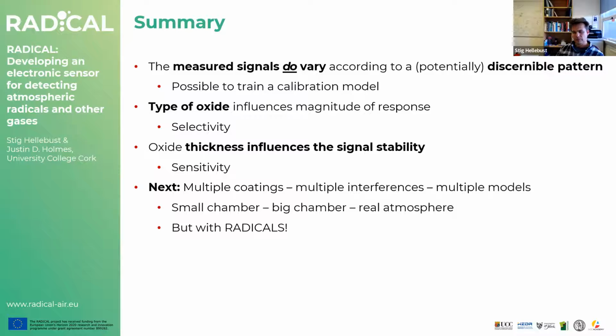So I think at this stage, this is early stage, we're talking to you before we have really most of the testing done. But I think at this stage, we do see that the gas phase and the nanowires interact in such a way that we can extract useful features from that. We want obviously to work on the selectivity, and for selectivity, it's important that the response has a certain magnitude, and also that the signal is quite stable. And we've seen that the surface coating will influence both of these features. So we have a lot of work ahead, but I think it's going the right way. So I'm going to hand back to Justin.